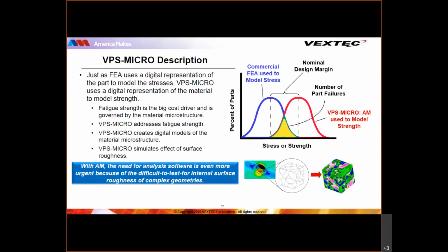And it's the random nature of this microstructure that drives the large uncertainty that we see in fatigue lifetimes, which makes fatigue testing so expensive and time-consuming, because you have to test a lot of specimens for a long time to understand what the true minimum fatigue properties are.